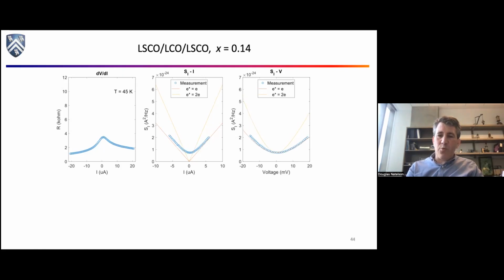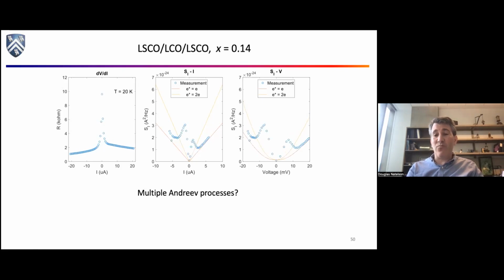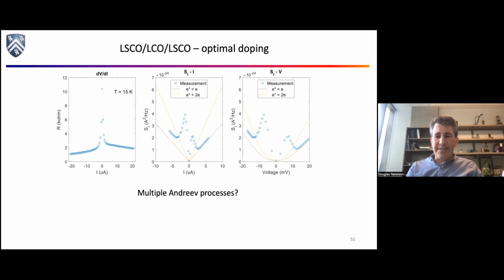As you cool down, this gets more dramatic. Here we are getting close to the superconducting temperature, and now you can really see there's quite some separation here. Right around TC, it's more pronounced. Now, when you get well below TC, complicated things happen, and you get really wild noise going on. I don't want to get into the details of this because it's a little bit beside the point. That sort of thing actually can happen in ordinary superconducting tunnel junctions as well. It's a complicated multi-electron thing that can go on. But the bottom line is that there are lots of deviations from single particle expectations way above TC.